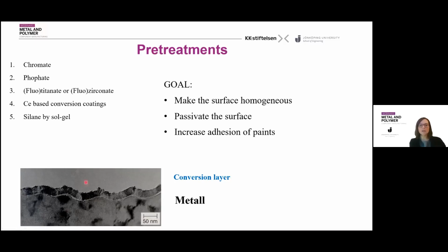So if you see in this microstructure, by pre-treatment we create a conversion layer, very thin, some tens of nanometers, on the metallic substrate. In this way, we first create a barrier, but also we create a controlled chemistry and microstructure at the surface in order to control the formation of bonding to the coatings.